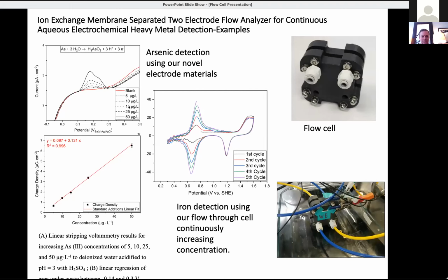And what we have here on the left-hand side is the results of the stripping of arsenic, which was pre-concentrated onto an electrode as a function of concentration. And so we have a blank, we have 5 micrograms per liter, which is below the EPA limit. 10 micrograms per liter is the EPA drinking water limit. And then we have higher concentrations, 15, 25, 50. And the integrated area under the peak follows a very nice calibration curve here.